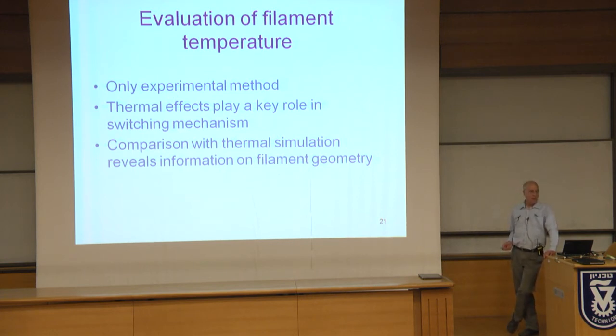Thermal effects play a key role in the switching mechanism. I think it's quite well understood that the switching can only take place at high temperatures, so it's important to know what the temperatures actually are. And we compare the thermal simulations with our measurements in order to extract some information on the geometry of the filament. That's what I'll be showing next.